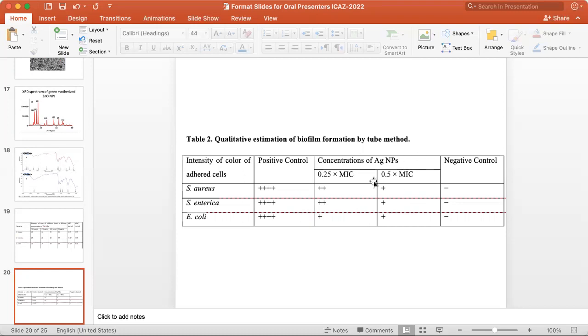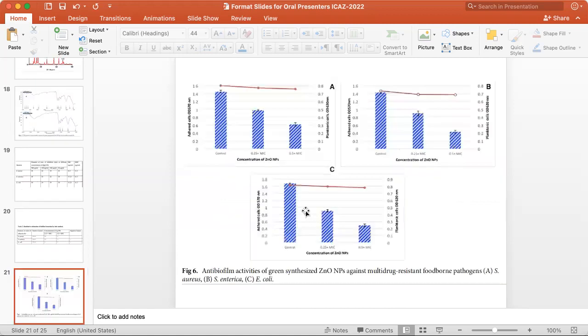Whereas by using nanoparticles at sub-inhibitory concentrations, these two concentrations were used. By increasing the sub-inhibitory concentration, the ring formation was reduced. So it means these nanoparticles were effective against biofilm formation even at sub-inhibitory concentrations.